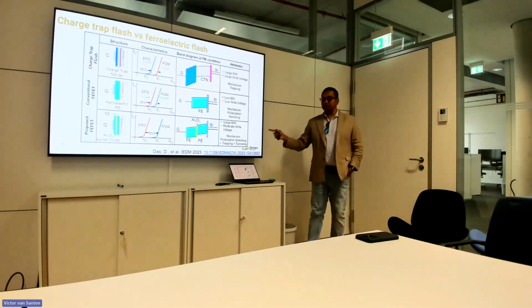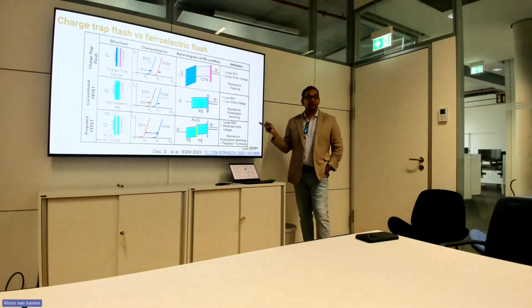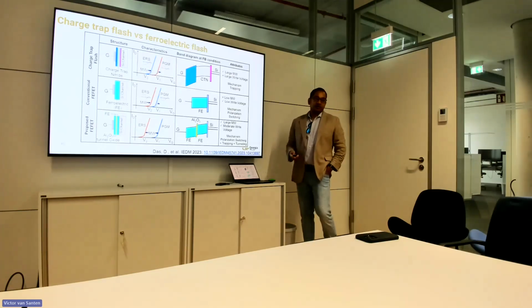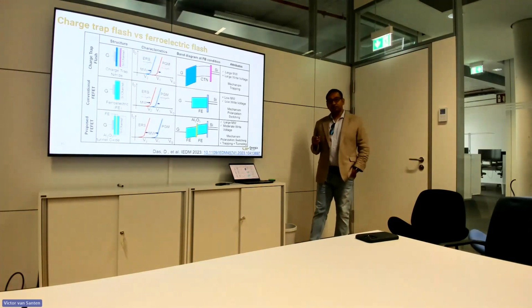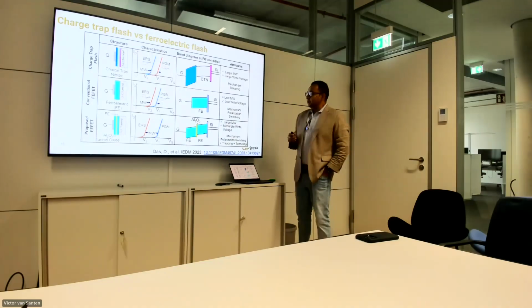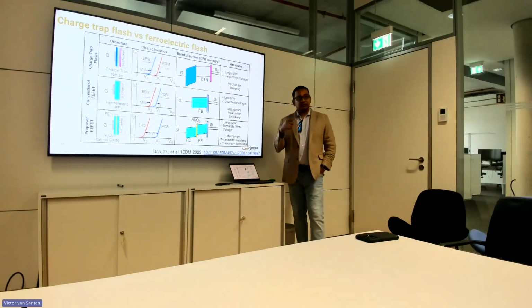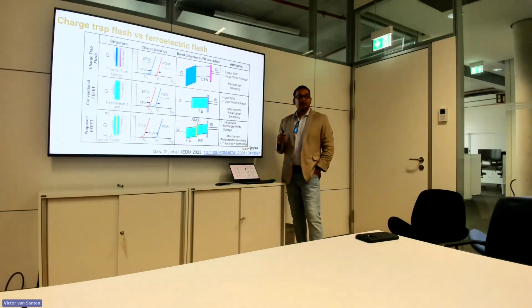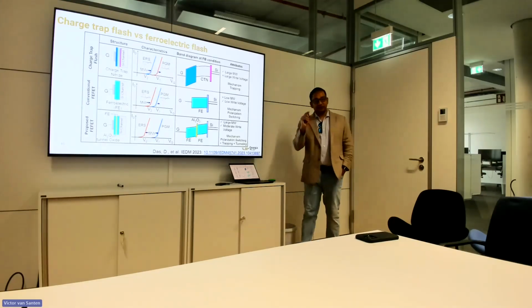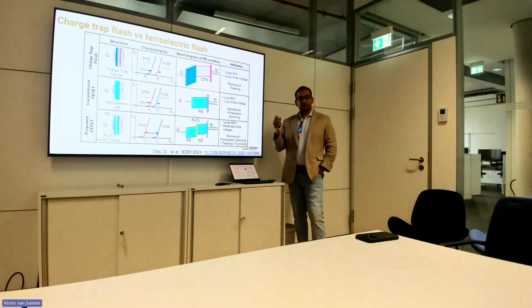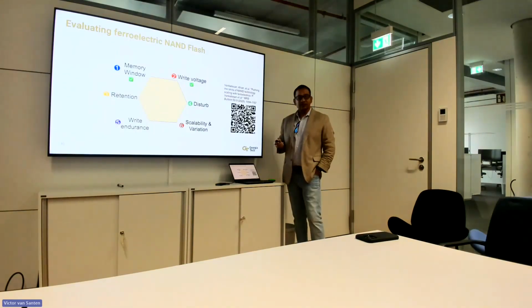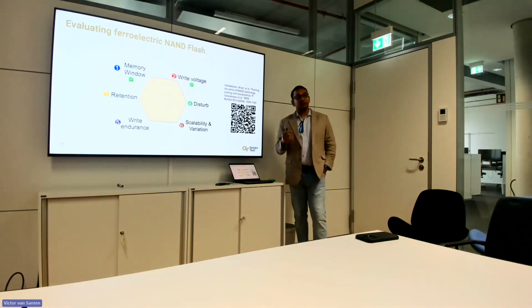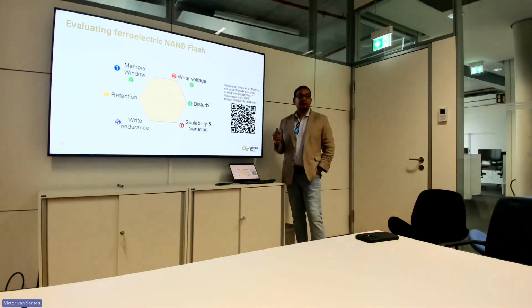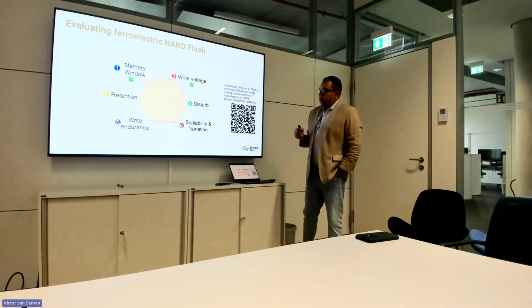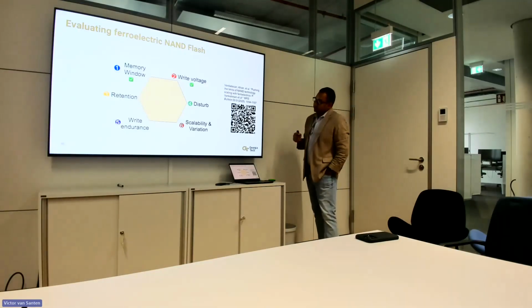And the second thing is the voltage is much less here, 15 volts versus 25. So the lateral charge migration will be much less. But of course, I'm very excited to see what we see in terms of lateral charge migration, because we're working on that right now to really scale devices and see how the charge trap increases. It's a fundamental problem because we still don't understand fully where this memory window enhancement is coming from. If we understand, we can solve all these problems.